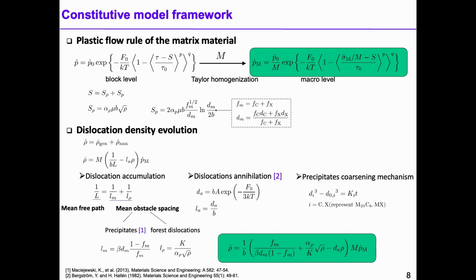The dislocation annihilation mechanism includes precipitation and forest dislocation effects. For the annihilation mechanism, the annihilation distance is governed by this formula, which shrinks the distance, and is temperature dependent. In long-term creep service, the precipitate coarsening mechanism is very important. The governing formula is this.